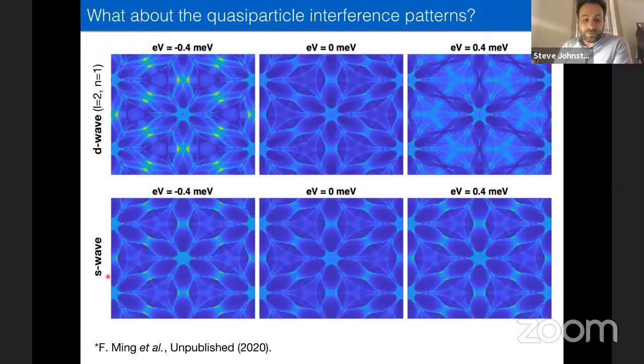If I put an S-wave gap into the calculation and repeat it, these disappear completely. So they are somehow related to the momentum structure of the gap. And so we know those flower patterns are at least inconsistent with an S-wave gap. We see them with this D-wave gap. The next question is, the D-wave gap has some momentum dependence. Is this related to the phase of the gap, or is it just related to the anisotropy of the gap around the Fermi energy?